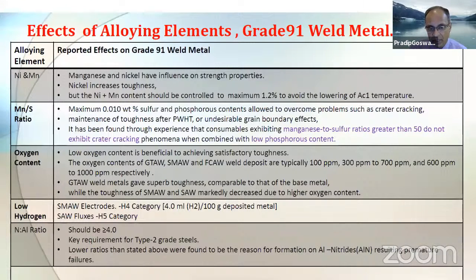That came out of the experiences which the thermal as well as various types of industries had faced over the years. So that is why, after taking a look at various failure histories, ASME around 2019 or so decided to control this ratio as far as these P91 alloys are concerned. But they didn't want to do it across the board. So they classified this alloy grade 91 into type 1 and type 2. And type 2 alloys, as I mentioned earlier, have this restriction.